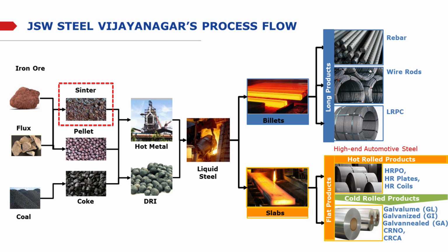The raw materials, that is iron ore, flux, and coal, are processed to produce sinter, pellet, and coke. Sinter, pellets, and coke are charged in blast furnace to produce hot metal, and pellets are charged in DRI shaft to produce DRI. The steel scrap and hot metal are charged in basic oxygen furnace to produce liquid steel. The steel scrap and DRI are charged in electric arc furnace to produce liquid steel.